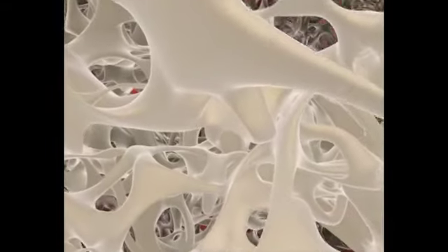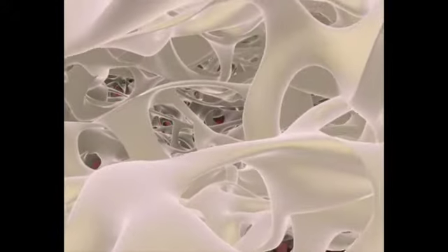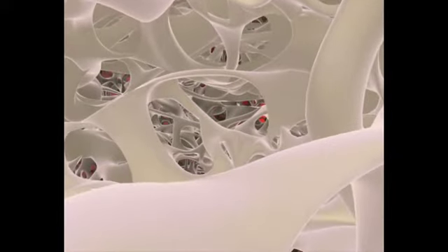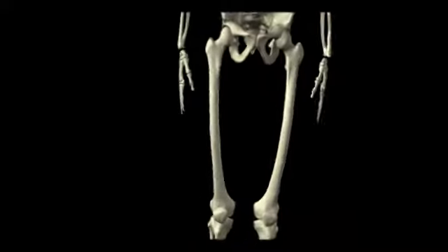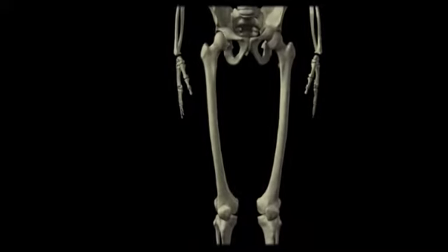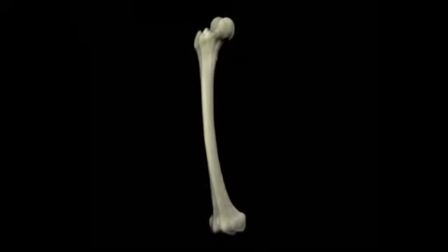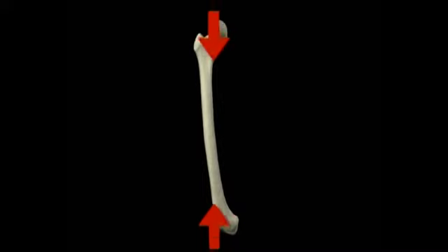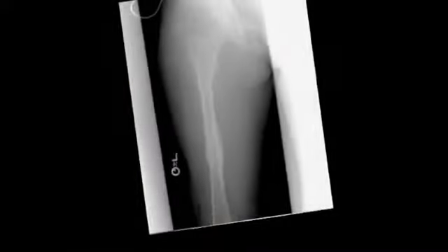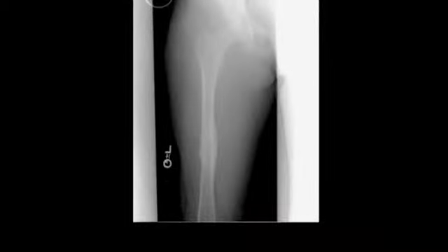During the remodeling phase, through both osteoblastic and osteoclastic activity, the medullary and periosteal calluses are resorbed, and the remaining woven bone or calcified cartilage is replaced by mature lamellar bone, which can be cortical or cancellous as the site dictates. Through remodeling, the biomechanics of the new bone are restored to be consistent with that of the surrounding bone. This is a gradual process, and radiographic evidence of the fracture can persist for many years.